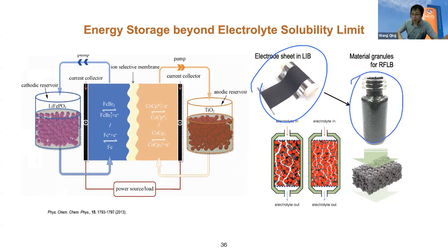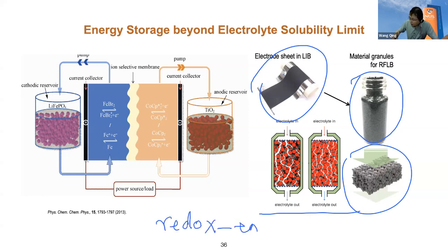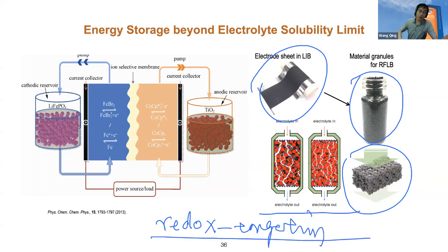If we have solid material, like the one I show here, with granules, big particles, it is just put into the reactor tanks, and the electrolyte just flows through and reacts with the solid material, which here is porous. So it can carry the charge from the tank to the cell or the other way around. Then we need a special process. We call this the redox targeting process. This redox targeting process is just one redox mediated process. It's between the molecule in the electrolyte and the material in a tank. When the molecule flows into the tank, it can react with the material. It can oxidize or reduce the material for different processes. Then the charge can be extracted or stored.